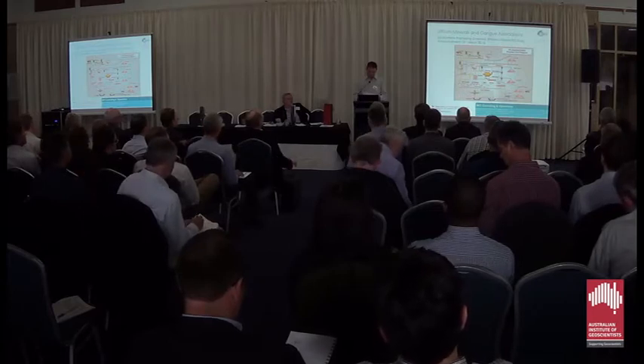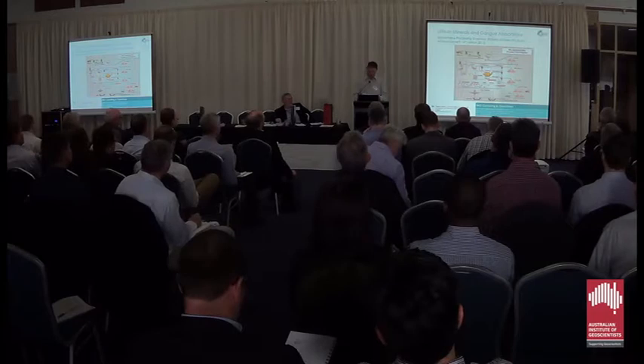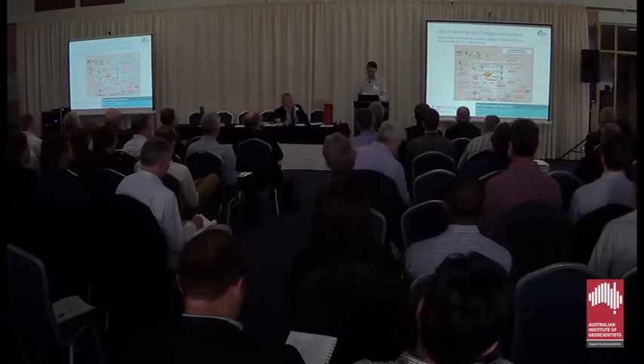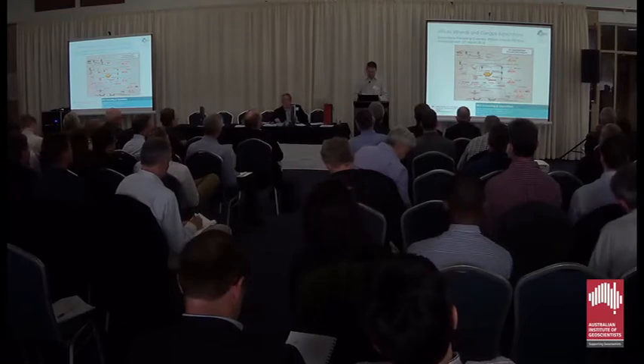It just means that the mass recovery during the rougher stage can be higher. The process generally takes longer to develop, and the circuit configuration and reagent blend employed requires more test work to develop as well. The rougher stage then undergoes multiple cleaner flotation stages similar to graphite. However, there are no regrinding stages in between the individual flotation stages to minimise slimes or ultrafines production, which for the majority of oxide flotation processes significantly foul the concentrate.